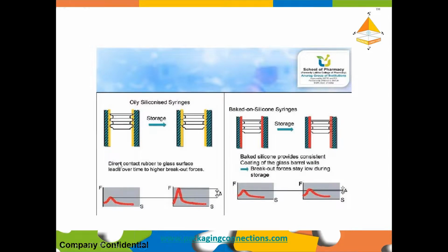See here, in the first picture, the yellow line is the silicone oil applied in the traditional way, and the rubber is continuously hitting the stopper here. So over a period of storage, this film may break, and then there will be direct contact between the rubber stopper and the wall of the PFS, which will create problems in breakout forces. If you have baked silicone oil, then that problem is almost eliminated, because the silicone oil remains and the film does not break. You can see the red line, there is no breakage in between. And when you compare the breakout forces, you could see here it could change, but here, it's quite consistent.